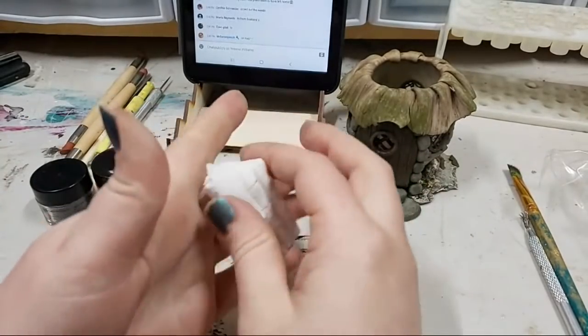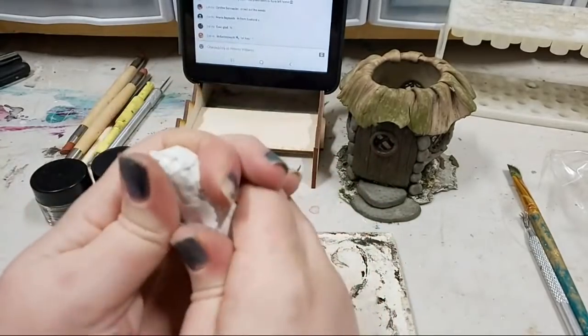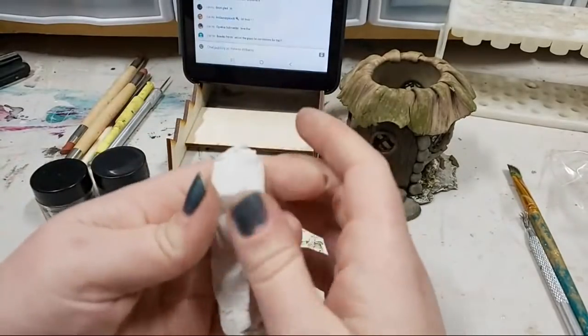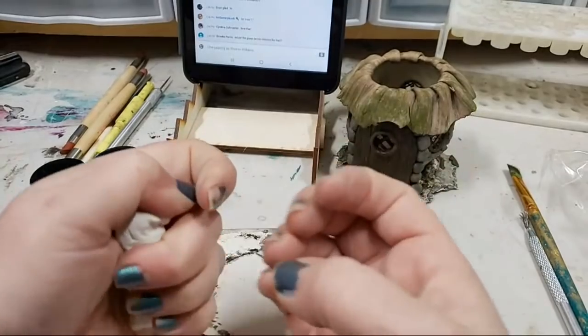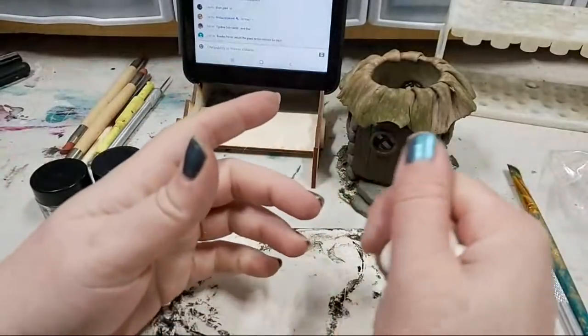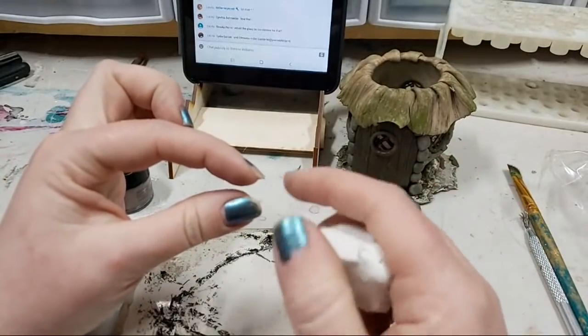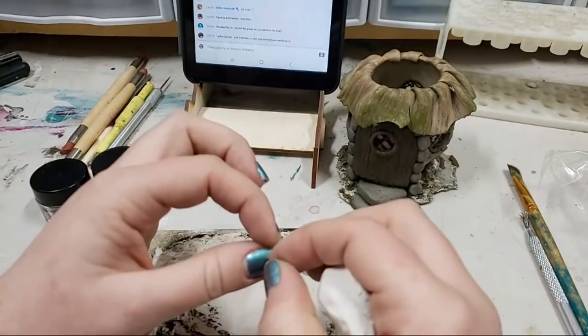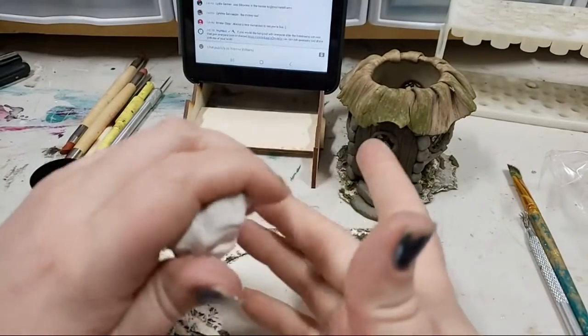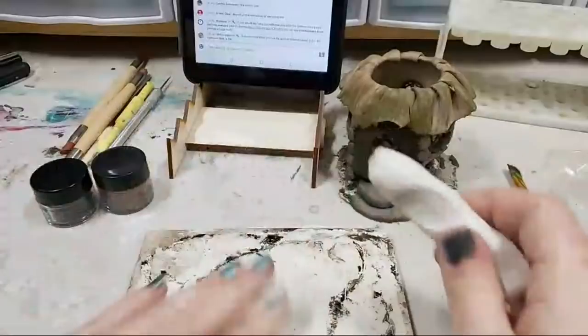Hey, Maria in Scotland. Thinking about getting bubbles out of glass. You can do what they call a bubble squeeze, where you bring it up to a certain temp and leave it there for about an hour, and any air would kind of seep out. But with the nature of what we're doing with the frit, every single piece of glass has a layer of air around it. So the more tiny pieces of glass we have, the more air bubbles it's going to make. Bubbles with frit are unavoidable.